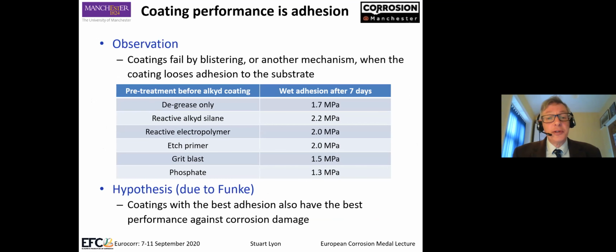Moving on a little bit further, coatings, of course, have to stick to the surface in order to survive. If they don't stick, they fail and corrosion occurs. So our hypothesis, due to Funke, was that coatings with the best adhesion also have the best performance against corrosion damage.